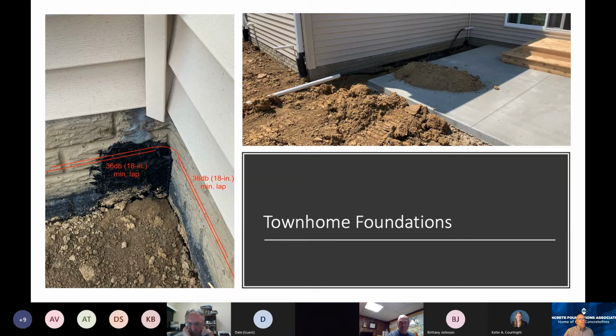They also got a crack along this wall, and this is the back side of the wall, and I'll show you a plan here in just a minute. But on the left-hand side, you can see right where the intersecting wall meets the long wall, they're getting a crack. Again, it's a filler condition. The form panel is full to this point, and then right where all the goop is, there's a small little filler that they put in because of the architectural dimension.